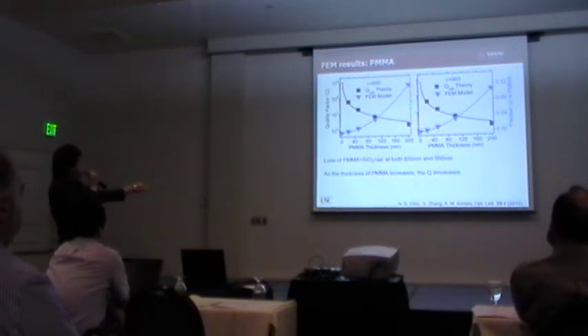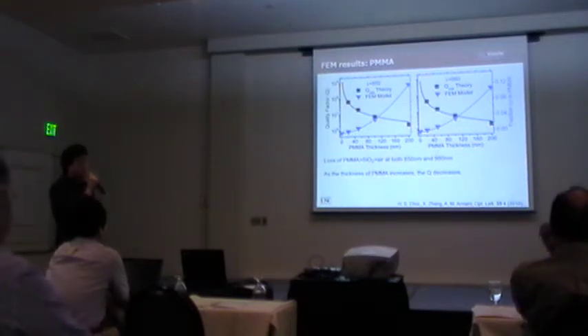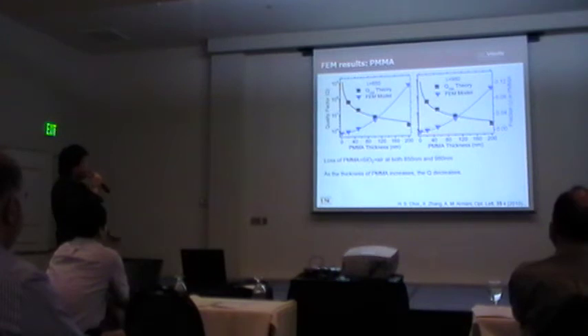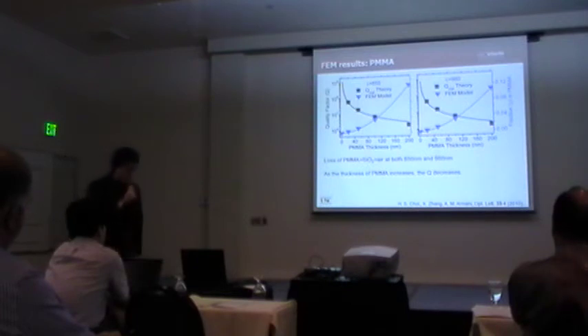Quality factor is highly dependent on PMMA thickness because the percent of optical field in the PMMA layer also changes with PMMA thickness. The percent of optical field in the PMMA layer is highly dependent on PMMA thickness because more optical field is squeezed between silica and air with a thicker coating of PMMA, because the refractive index of PMMA is higher than silica and air at both wavelengths. To summarize, the loss of PMMA is higher than silica and air at both wavelengths. As the thickness of PMMA increases, the Q factor decreases.